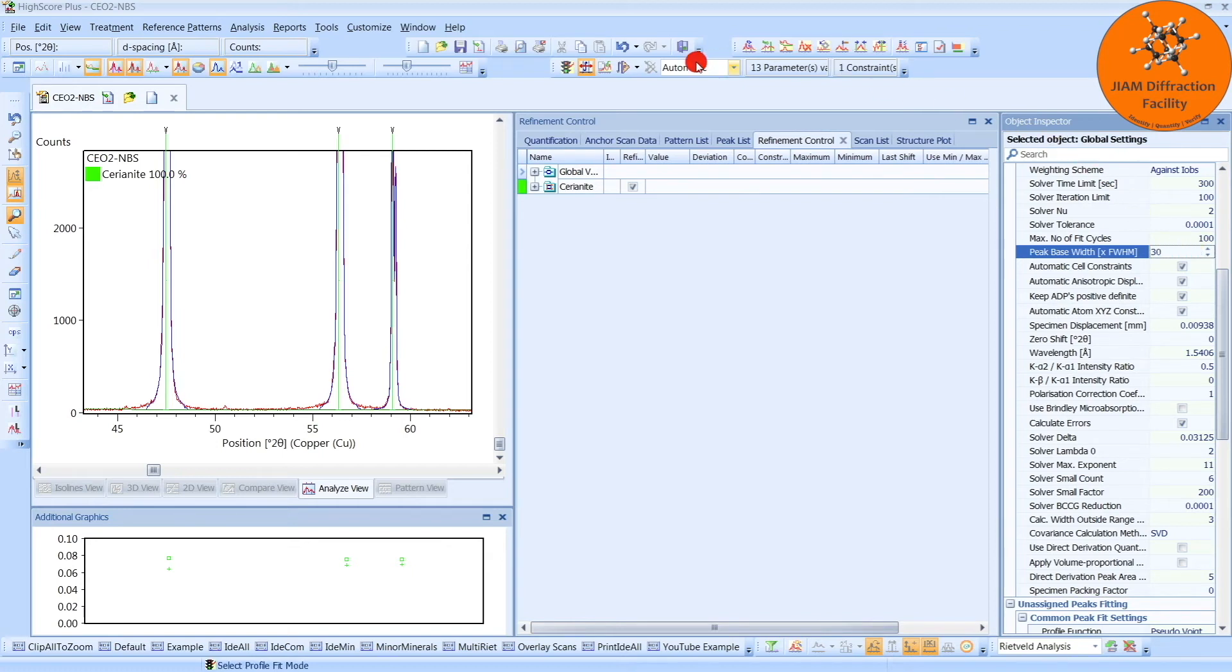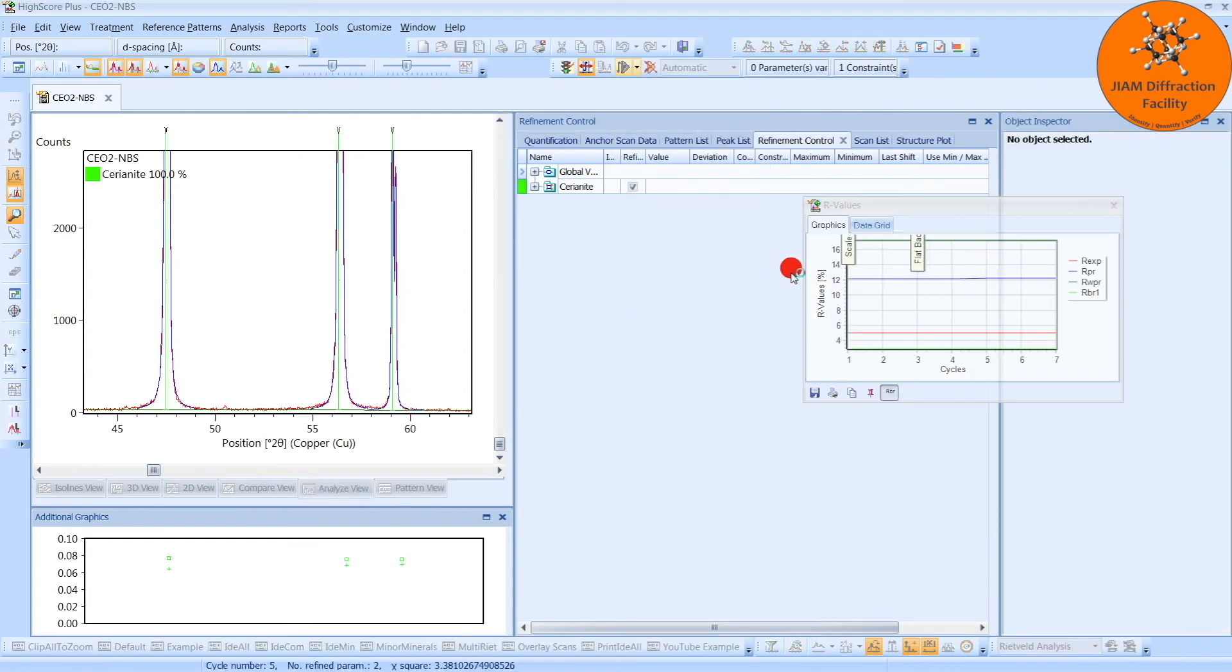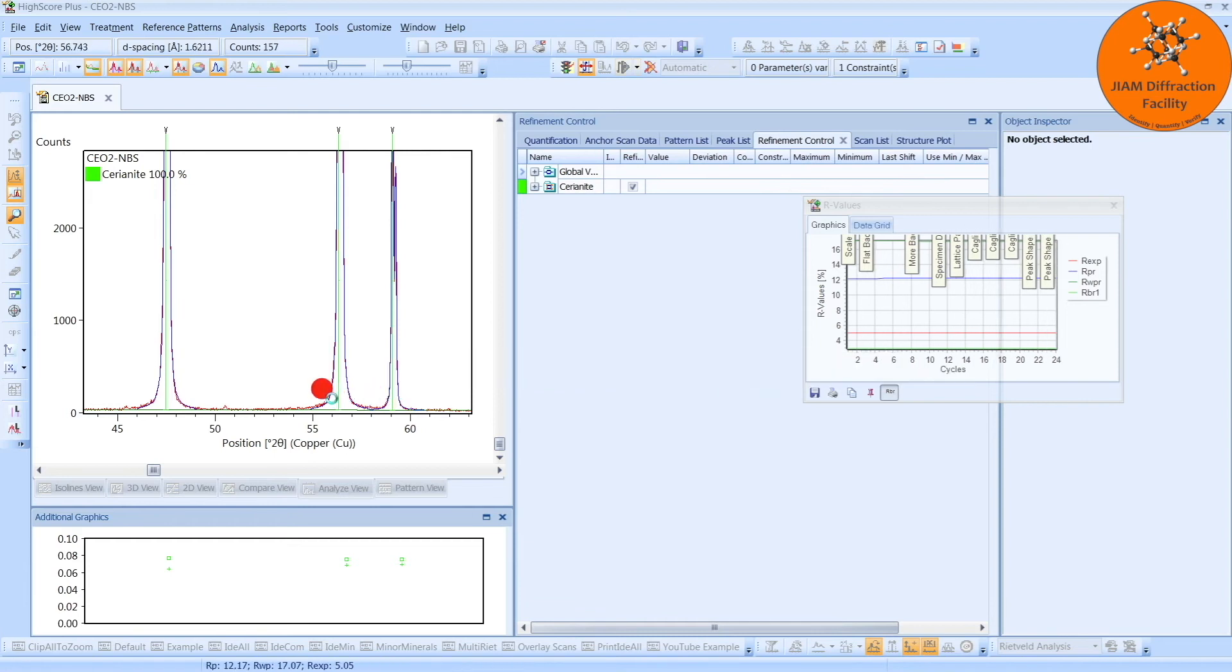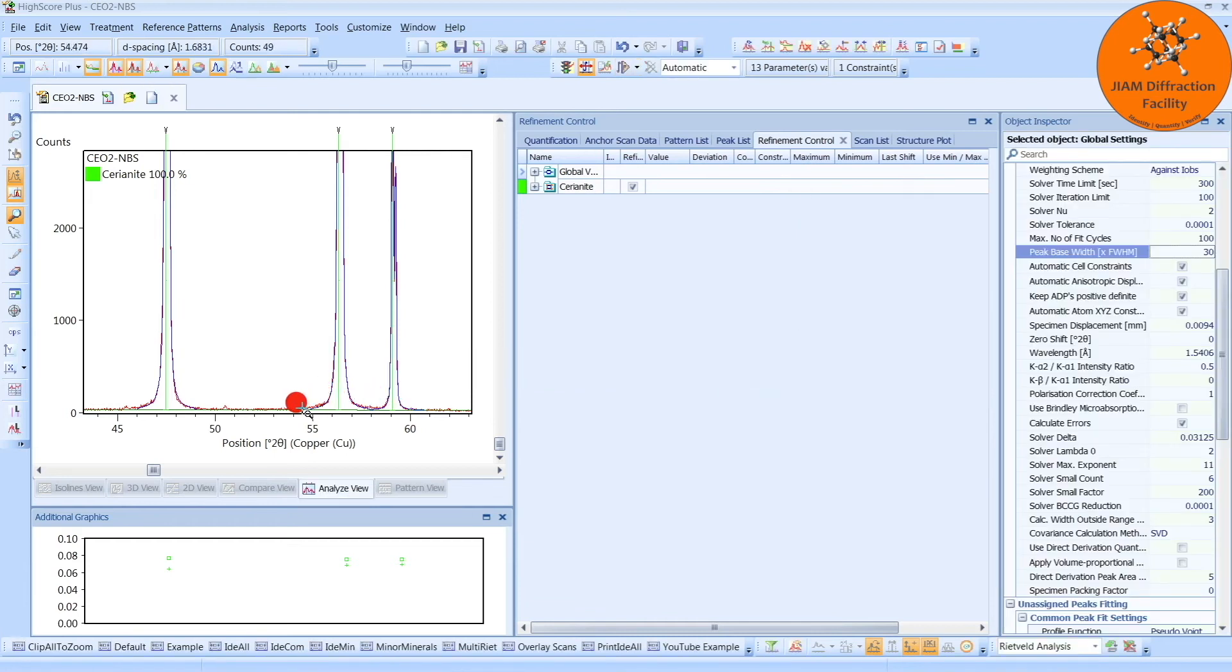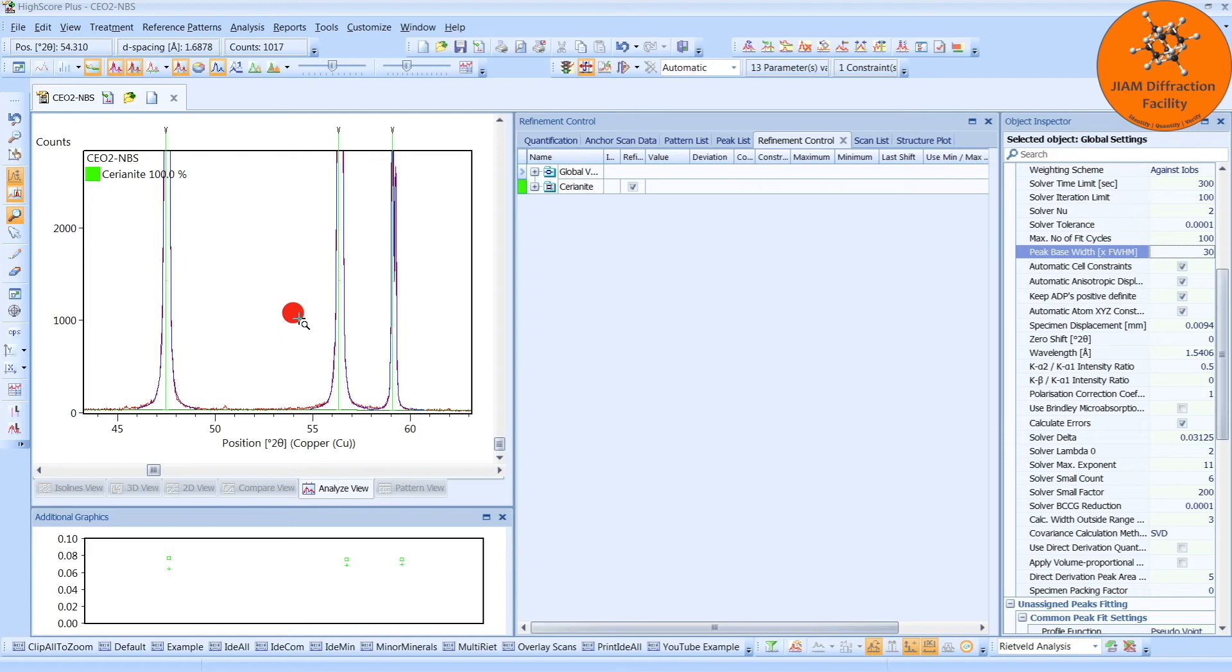So let's change this to 30. And then come up here. And perform another size strain analysis R fit. And now we see that our blue curve matches up more nicely with that red curve. If you are analyzing other data, I will let you zoom in on these low intensity regions to determine what your peak base width should be. Maybe you need a smaller number or a larger number. It all depends on your pattern.